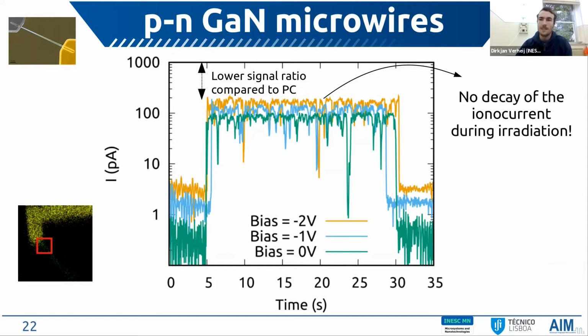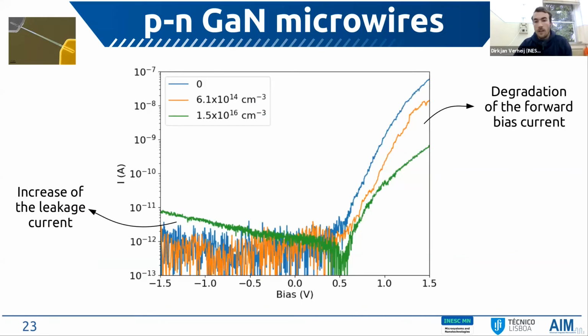So what actually happens is that the protons cross the wire and only deposit part of their energy in the active area. So this could explain why we observe a lower signal ratio compared to the photocurrent measurements. So then finally, I want to also show you the evolution of the dark current with increasing fluence, or with proton irradiation with increasing fluence.